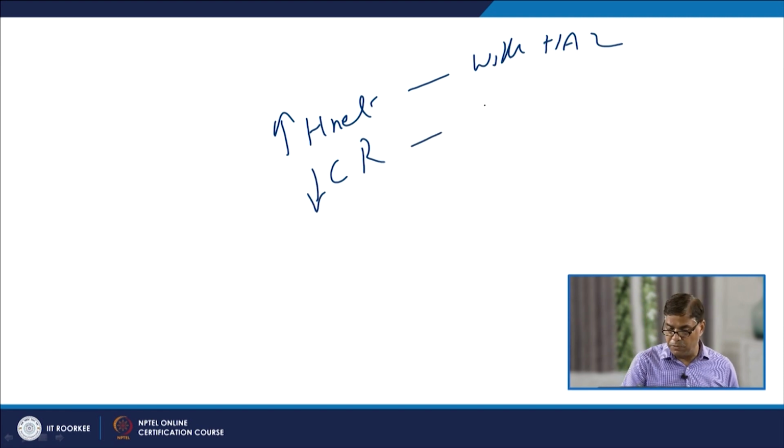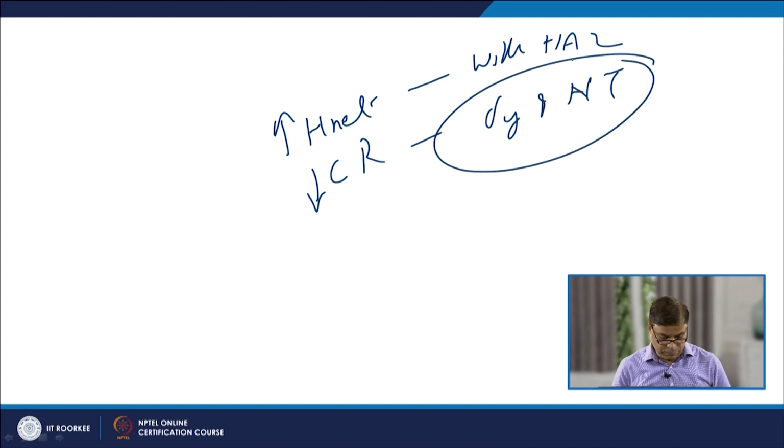So, this deteriorates the yield strength and notch toughness of the cut edge of the steel, and that compromises the mechanical properties of the cut edge significantly. So, that is why the gas cutting process is normally not used for cutting of QNT steel.